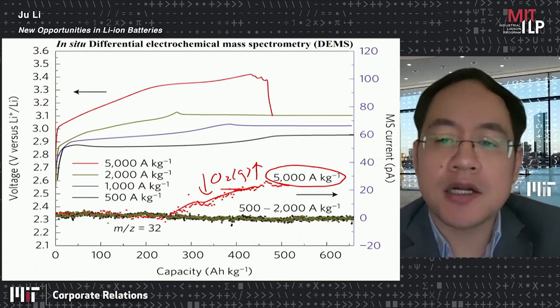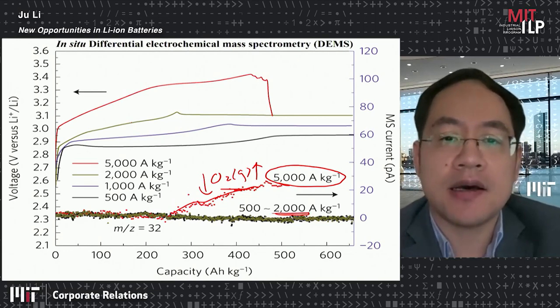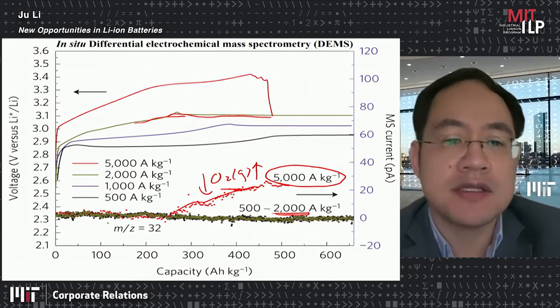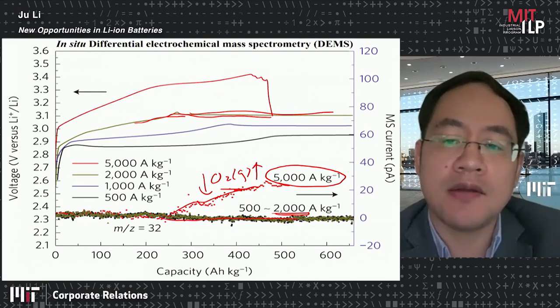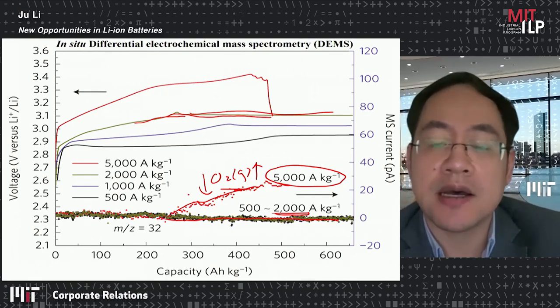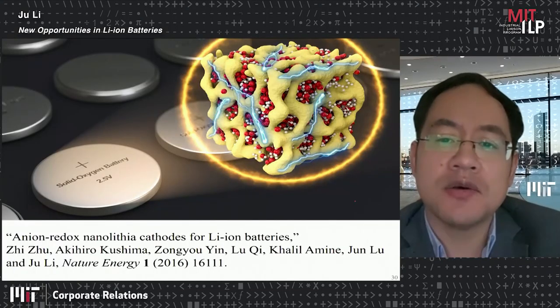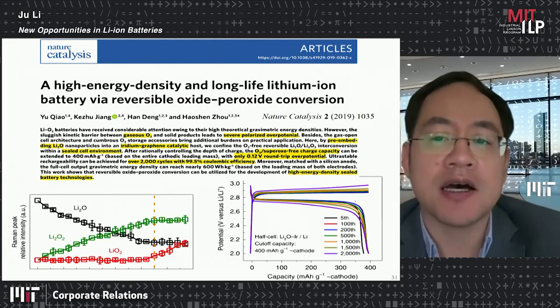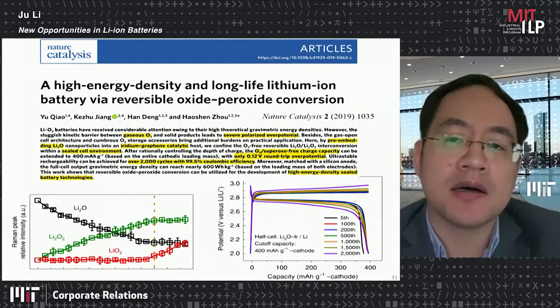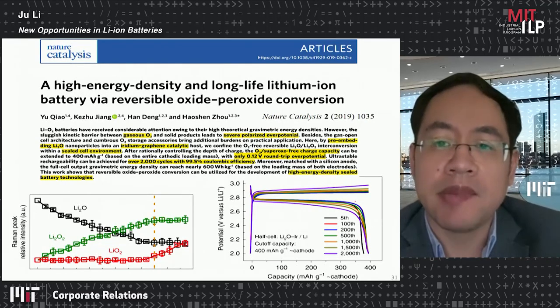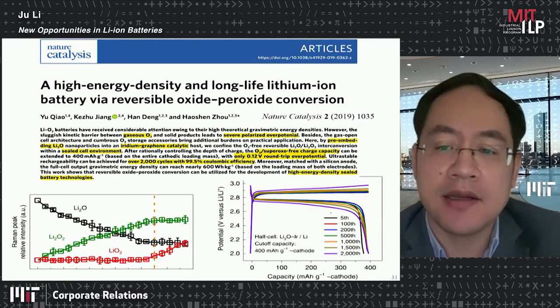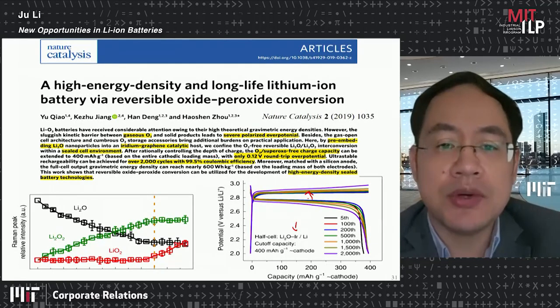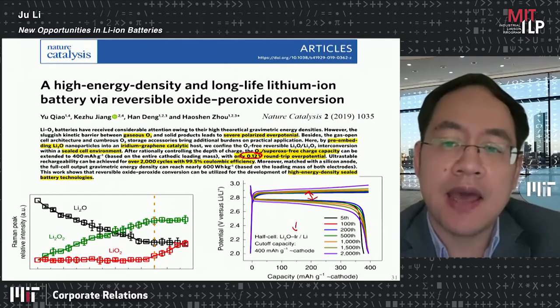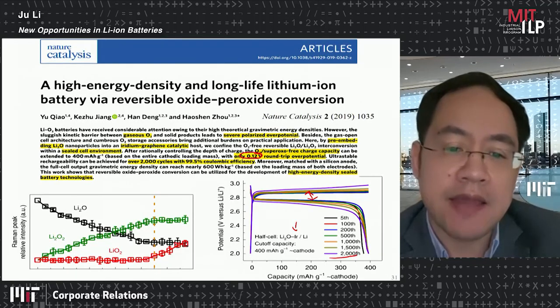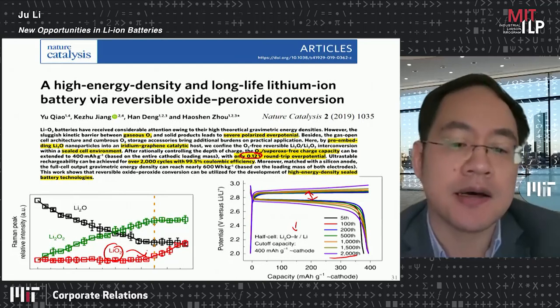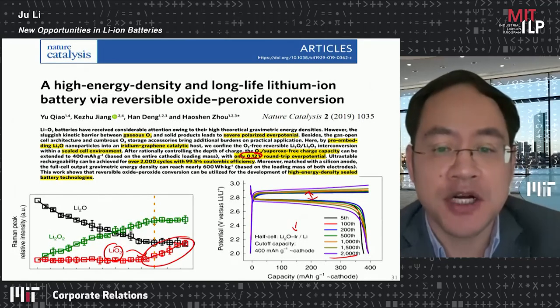But if we charge at something like 4 C, then actually this is the charge voltage. It doesn't go up again, and we can stabilize the system with no oxygen release. So this result was recently scaled up by very impressive work from Japan and Nanjing University, where they've shown using iridium catalyst, they can reduce the overpotential to only 0.12 volt, and they can cycle up to 2,000 cycles. And they have also verified that there is lithium superoxide at the end of charge.